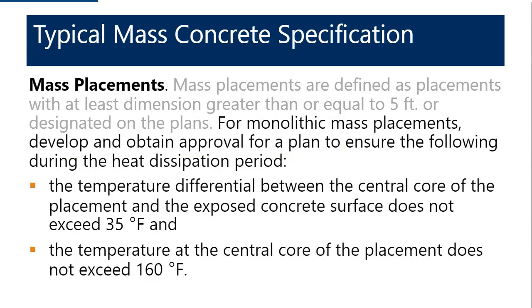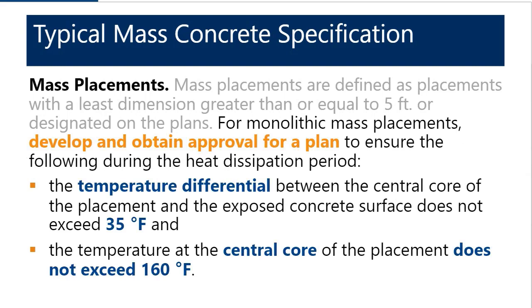Now, once you've defined the mass concrete elements, there's another component of the specification that we'll visit. So this is actually the same DOT specification language I showed earlier, but now I'm focusing on the second half of the definition. And what it shows is that once you've defined the mass concrete placements, the next step is to develop and obtain approval for a plan, or a thermal control plan, that ensures that the temperature differentials do not exceed 35 degrees, and that the temperature of the central core, or the interior of the placement, does not exceed 160 degrees. Now, these limits can change from specification to specification, but the basic concept is the same, that a thermal control plan is developed to control the temperature differentials and the central core temperature of a concrete placement.